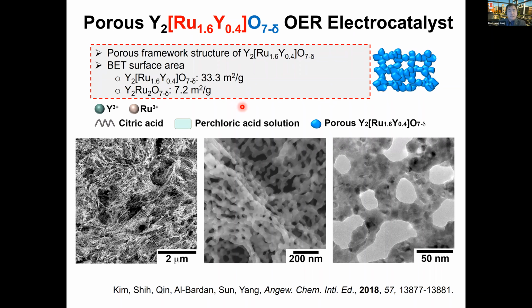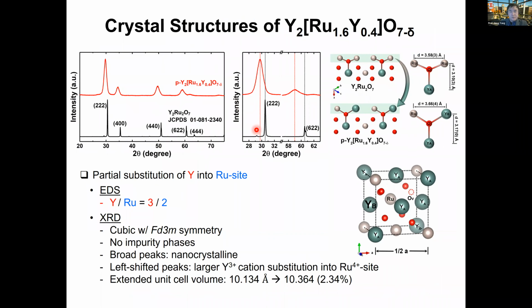For this particular type of catalyst, this is what I tried to highlight: besides the pores being generated, we also have the yttrium going into the B-site, i.e. the A-site metal goes to the B-site. This anti-site creation leads to a different performance later on, we think. On the right-hand side, as you can see, this is where we propose the structure differences from the traditional pyrochlore structure with an A2B2 structure. Because the ratio between these two is a 3:2 structure, under our synthetic conditions for porous generation, that turned out to be the most stable composition.